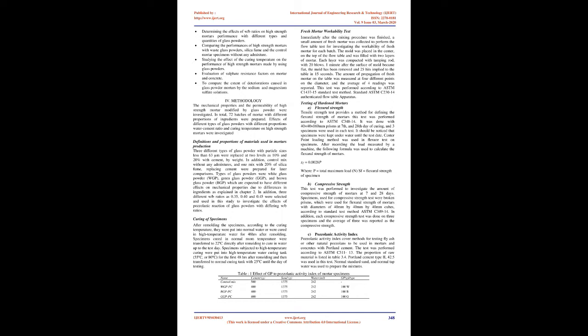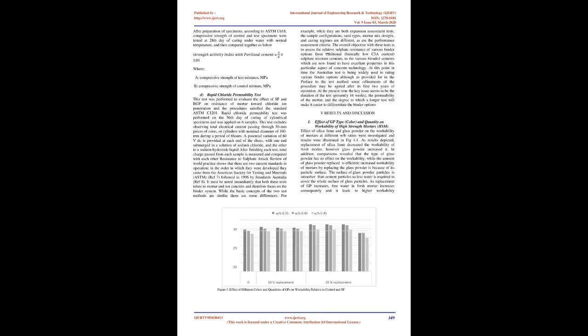Kumar Uppun et al., 2013, for the fresh phase of concrete. Some researchers demonstrated that replacement of cement with glass powder up to 40%, with a particle size less than 300 µm, could increase the slump from 40 mm up to 160 mm. Another research also showed that by increasing the amount of glass powder in concrete, the slump also increased.